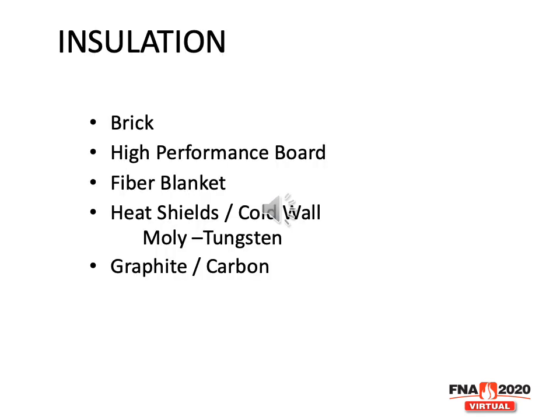Insulation in furnaces can be things like brick, high-performance board, fiber blanket. You can also use heat shields. They're called cold wall. They're usually moly or tungsten, and even graphite and carbon. The issue is when you get to graphite and carbon, you have to make sure the O2 levels are very low. Otherwise, they just disintegrate.